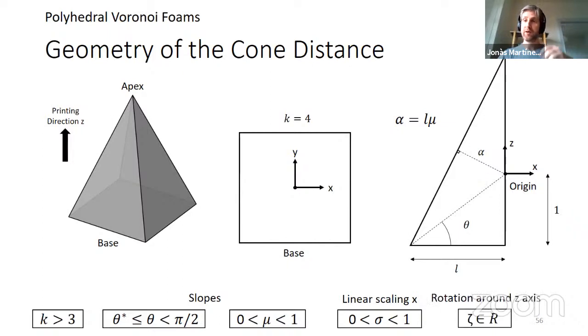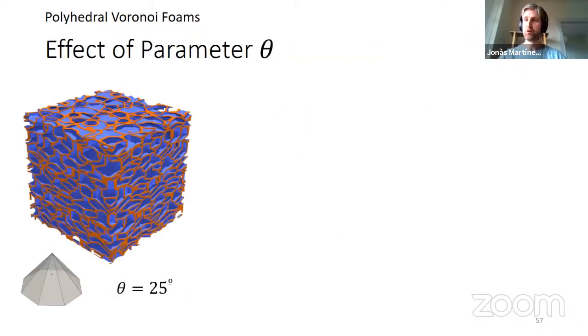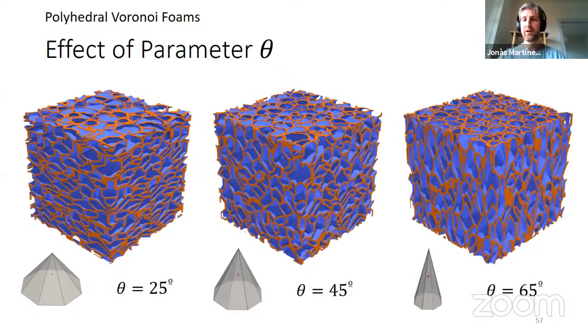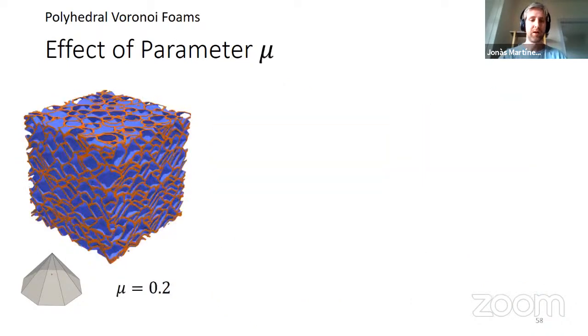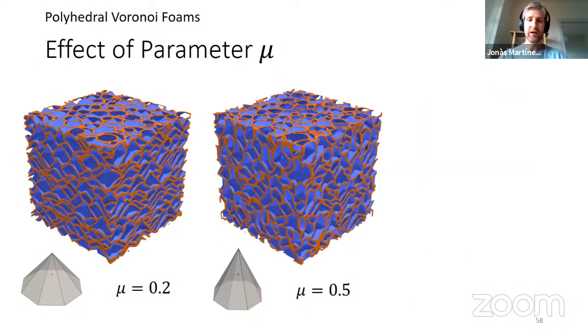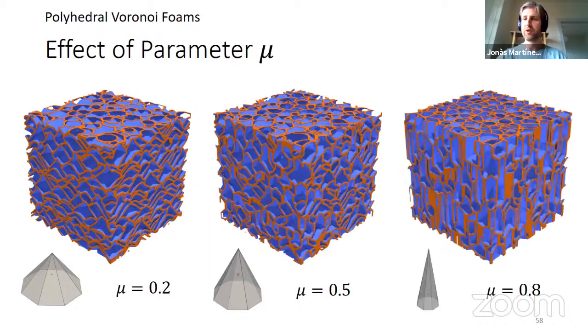And finally, what we can do is we can rotate this cone, of course. So here, let's see a visual explanation. Here, for instance, if the origin in the interior is fairly down, we get a 25 degrees minimum overhang angle. Here we get 45 degrees, and here this one is pretty strict, we get 65 degrees. So that's one possible parameter. We usually fix it to 45, but the user can choose it. The parameter mu controls basically the aspect ratio. So intuitively speaking, you can get either more vertical faces or less vertical faces from left to right.